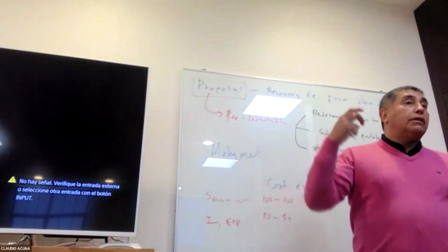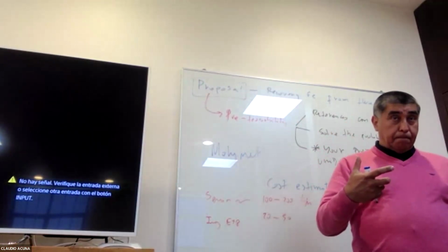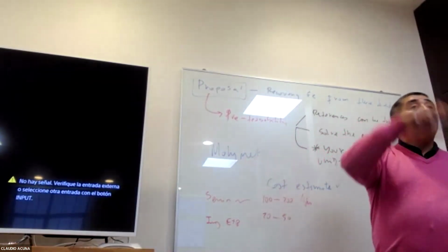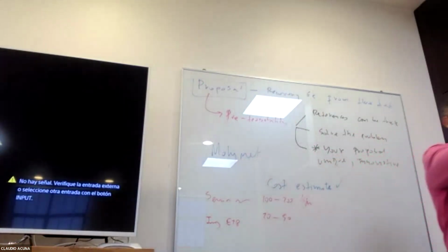Why is it important? You can check a Chilean company called Monument, because they want to extract critical elements from tailings. It was a mine in the US. What happened with this company? I don't remember how much they lost. They invested, created the project, but they had the wrong sampling and they lost a lot, it's public, a lot of money because the plant didn't work. Because the original characterization is really, really heterogeneous. It changed a lot. Especially tailings.